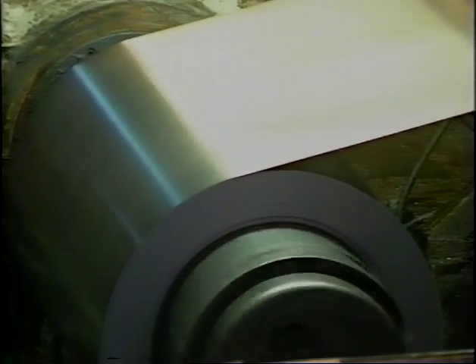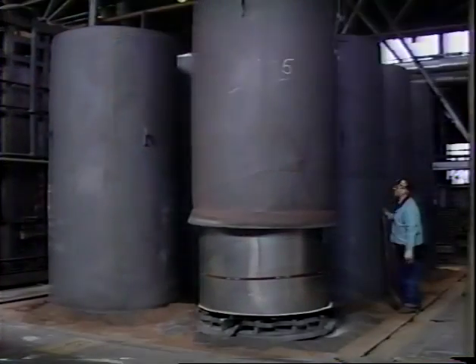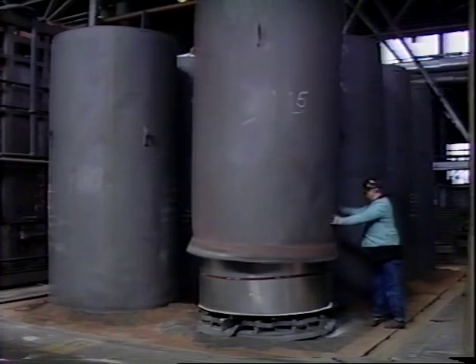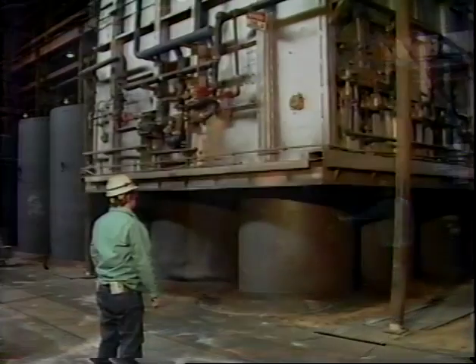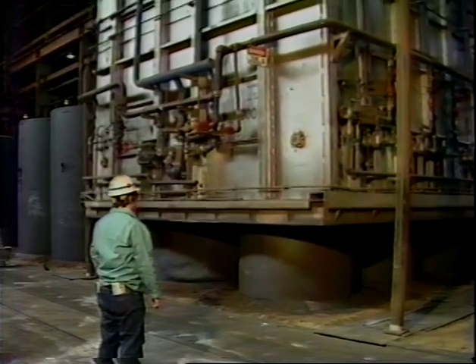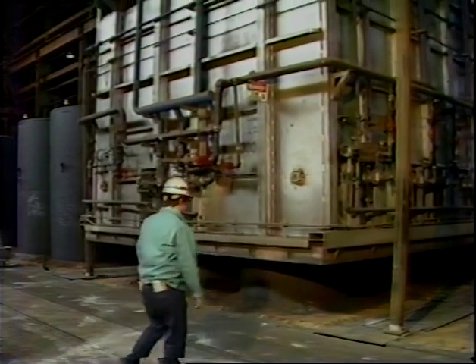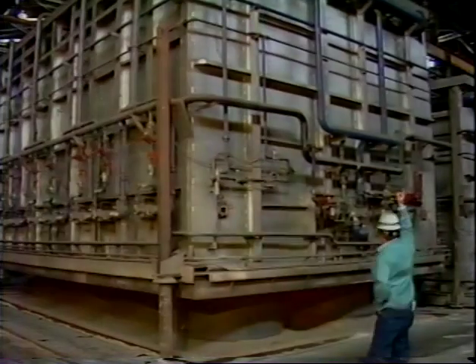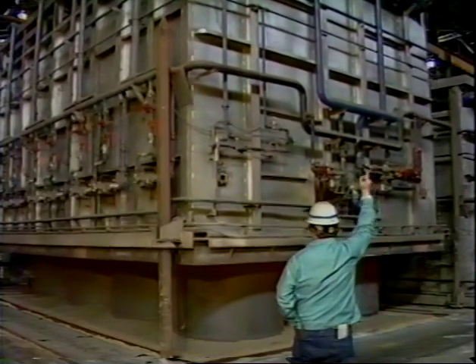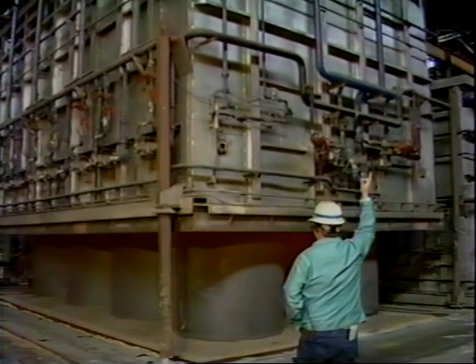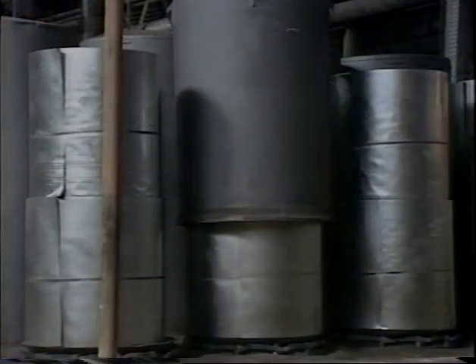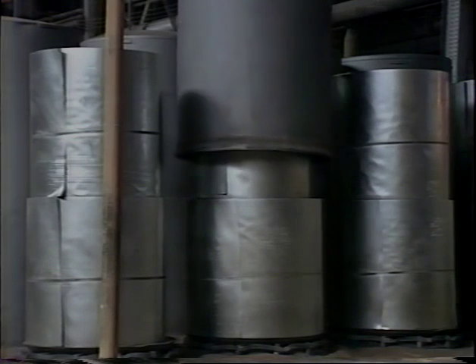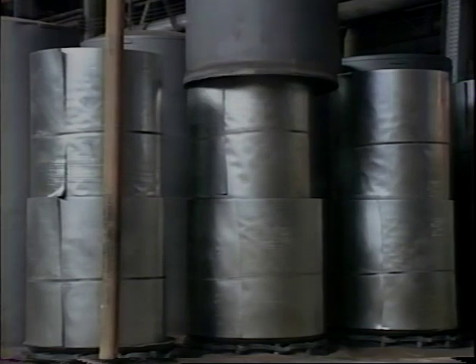But cold rolling hardens steel, making it difficult to form in most applications. To make the steel softer, more ductile, we box anneal it, carefully heating and soaking the steel in a controlled atmosphere. The annealing furnace heats the coils uniformly and holds them at temperatures from 1050 to 1350 degrees Fahrenheit, depending on the mechanical properties the customer needs. Then the steel is slowly cooled to a point where the furnace and inner cover can be removed with minimum oxidation. The annealing process takes about a week, and the steel emerges with a recrystallized grain structure for maximum formability.